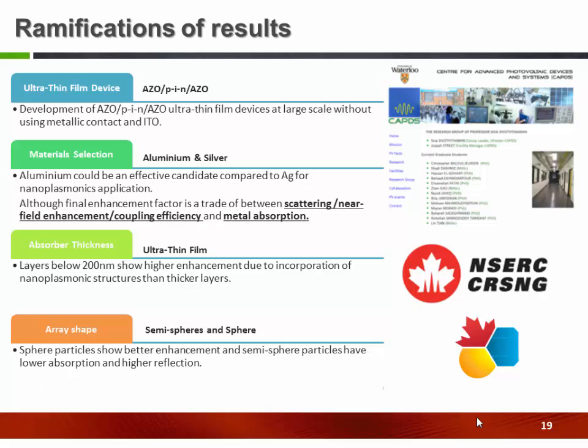So if I want to summarize my results, I could say that the development of one of the ultra-thin devices based only on aluminum doped zinc oxide was one of the achievements. Due to the low efficiency, 4% efficiency, we are trying to use the nanoplasmonic structure for the enhancement of these devices. And considering the application that we are looking for, which is semi-transparency, we decided to use aluminum instead of silver for further enhancement because of the low parasitic absorption and better reflectivity of aluminum. So we are going to use this structure on the back of our devices.